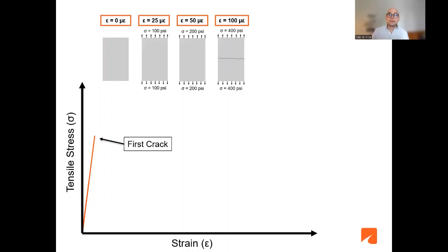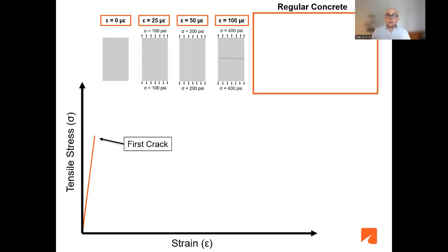Now, the question is, what happens after this crack? If it is a conventional concrete material without any fiber reinforcement, you're going to have a brittle, immediate failure of this material. And again, imagine the culvert repair, when you have this structural repair. If the concrete material that you have there does not have any fibers and you have a crack, you know that that concrete can no longer hold the load. So this could be very problematic if the host metallic pipe further deteriorates to a point in which the concrete material actually has to hold the load.